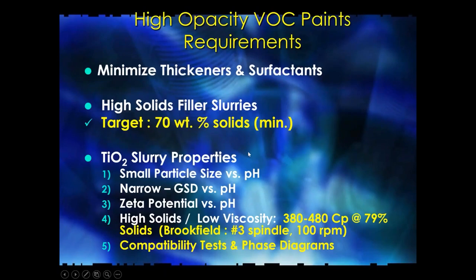Now, the other thing is what sort of slurry properties you want. So here's where the Horiba comes in. You want a small particle size versus pH. How are you going to measure it with particle size? I want a narrow particle size distribution versus pH. How are you going to measure it? Horiba. I want zeta potential versus pH. Why? Because if I try to do my dispersion and it's a positive charged product and I've got negative charged resin, it's not going to work. I want high solids. And by breaking particles down into the smallest form prior to making your paint, you are going to have the best possible paint.